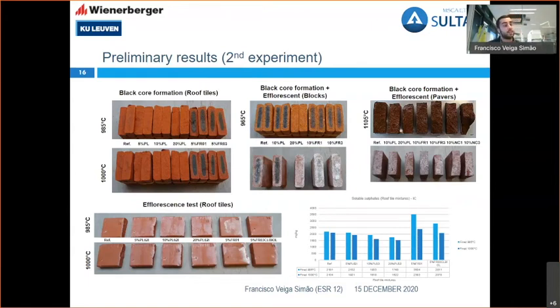On the pavers it is really a different mixture, and you fire higher. So you see a kind of similarity also in the efflorescence marking, even though it's not represented here. This is the soluble sulfate content of the roof tiles, but indeed there is a slight increase towards this more uncleaned material in the soluble sulfate content, which also shows slightly more efflorescence marking.